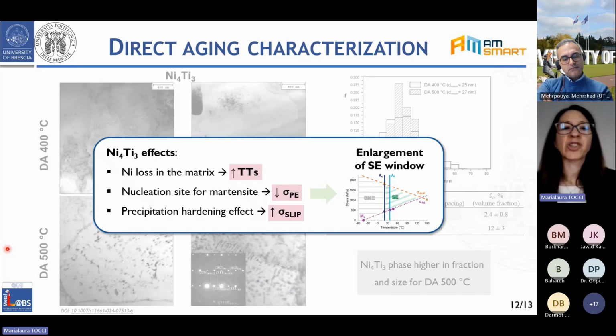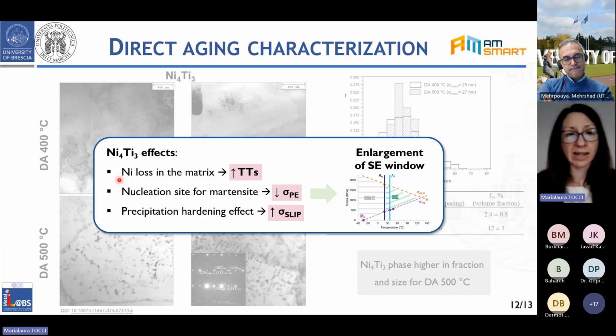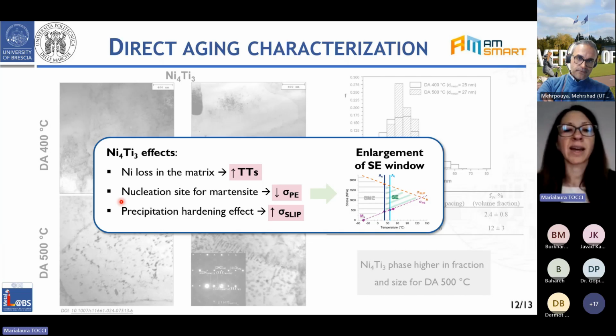So, what is the contribution of these precipitates? They play a fundamental role in enhancing the superelastic behavior, because the formation of these precipitates causes a loss of nickel in the matrix that is responsible for the increase in the transformation temperature. They are also nucleation sites for the martensite formation, and therefore they contribute to reduce the pseudoelastic stress. And on the other hand, they harden and strengthen the matrix, contributing instead to increase the critical stress for slip deformation.